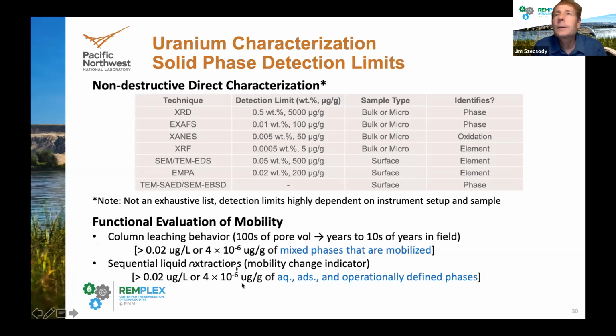Now, I'd like to point out that these aqueous concentrations that can be measured have very low detection limits, lower than surface phase techniques. So they're useful for most field sites, even at very low uranium concentrations. So you get a measure of what uranium is leaching out of the sediment, but you do need those surface techniques to tell you what exactly it's leaching from.